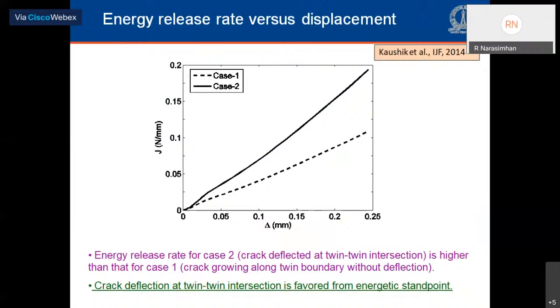The most emphatic thing in our simulation is this plot here, which shows the energy release rate versus load point displacement corresponding to the two cases. Case 1, remember, is the situation where the crack is allowed to grow along the twin boundary without any deflection, and case 2, where the crack is taken to deflect at the twin-twin intersection. This clearly shows the energy release rate for case 2 is much higher compared to case 1, almost by a factor of 2, corresponding to load point displacement of about 0.25. So this establishes that crack deflection would be favored at twin-twin intersections from an energy release rate standpoint.